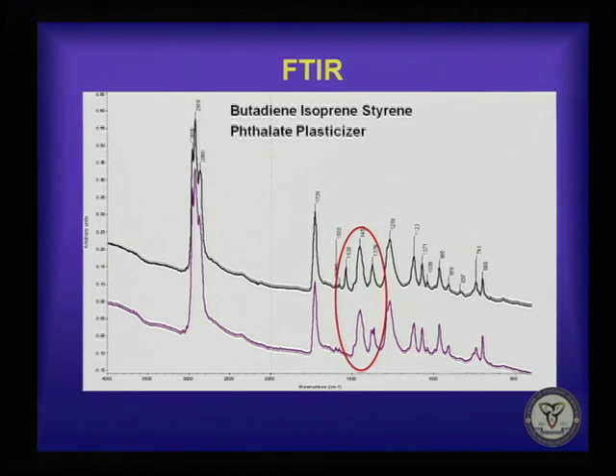And here's an example to show you two spectra of two tapes that we were able to discriminate. You can see in the area that's circled in red, there's a peak at 1539 that's present in the top spectrum and not in the bottom. And then there's a doublet at around 1370 that's present in the bottom spectrum, and there's only a singlet in the top spectrum, and that's from the tackifier.